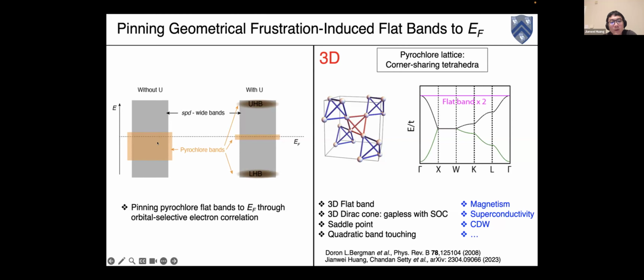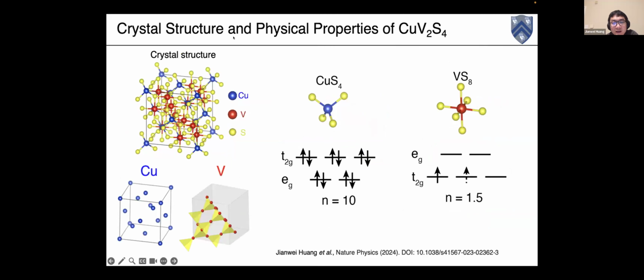The strategy is that these pyrochlore bands with this flat band are likely to be more susceptible to the electron correlation effect. For example, if we switch on the electron correlations, the pyrochlore bands could be strongly renormalized, with a coherent state very close to the Fermi level, and the incoherent bands being the lower Hubbard and upper Hubbard bands. And it turns out this is really the case in the material called copper vanadium sulfide, CuV2S4. This material has a vanadium pyrochlore sublattice and also a copper diamond lattice.